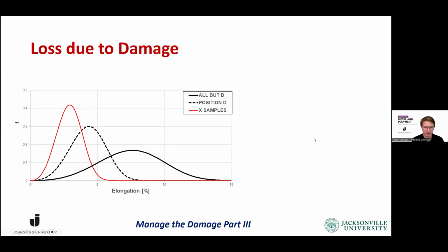So the solid black curve is the distribution for all positions except the D. So even if we have good samples and bad samples, they all come from the same distribution with an average of around 7-8%. But it's quite a wide distribution, and that's the general material quality or elongation level that we have in this material. The black dashed one is position D, and you can see that it is clearly following a distribution which is different, and it has a much lower average value of around 4%. So it's clearly different.